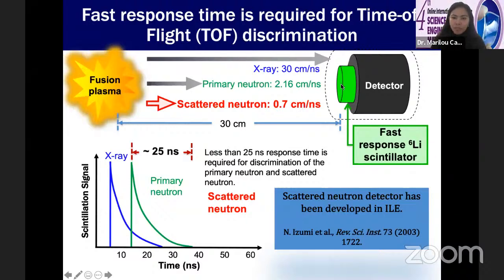So by having a fixed distance and different speeds, that means that these X-rays, primary and scattered neutrons, arrive at the detector at different times. X-rays are the fastest, so they arrive first, followed by the primary neutrons, and then the scattered neutrons. So if we calculate the time difference between the arrival of the primary neutrons and the scattered neutrons, that will be around 25 nanoseconds of time delay between the scattered neutrons and the primary neutrons. So that means that the scintillator used to detect the scattered neutron should have a response time that is 25 nanoseconds or faster, so that it's able to detect only the scattered neutrons. And before the next X-ray pulse arrives, that detector would have decayed to around 0 levels.